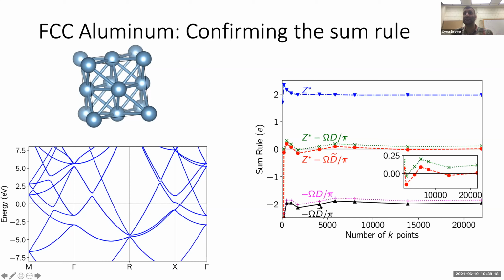And if we look at the negative of the Drude weight, you can ignore the purple dotted line for now. I can come back to that if there's any interest. But considering the black line, it takes a while to converge, but once it does, it also converges to a value of around 2. And if we add the two together, just focusing on this red curve, we can see that it converges basically to 0. The sum rule is accurately satisfied for FCC aluminum. Okay, so that's a nice test of the methodology.